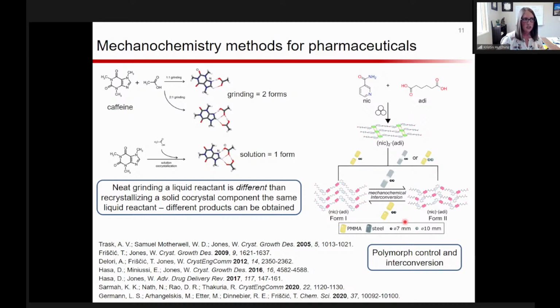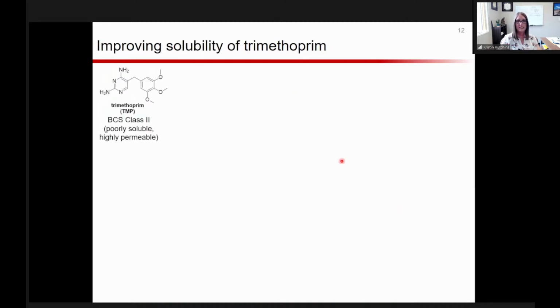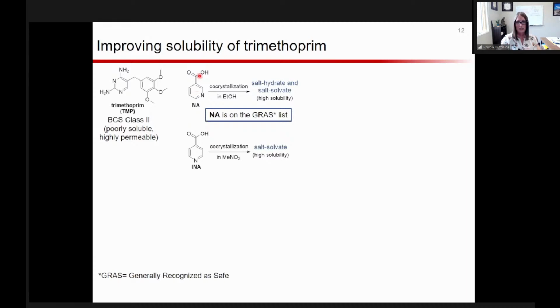And so the first story I want to tell you about with the pharmaceuticals is that of trying to improve properties. And so we chose the drug trimethoprim, which is a BCS class 2 drug, meaning that it has poor aqueous solubility. And we decided to co-crystallize it with nicotinic acid. So nicotinic acid is on the generally recognized as safe list that the FDA puts out. And we typically try to choose compounds that are generally safe so that if we want to put those into pharmaceutical co-crystals and give them to patients, we know that it's non-toxic. And so nicotinic acid was chosen for that reason.